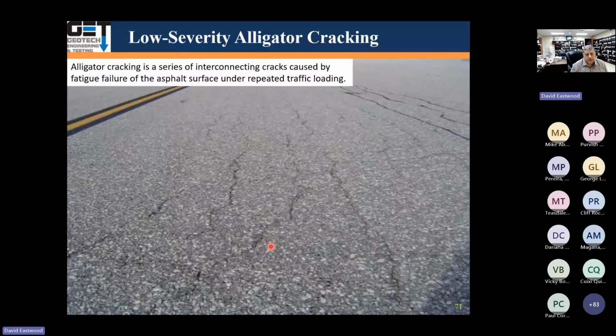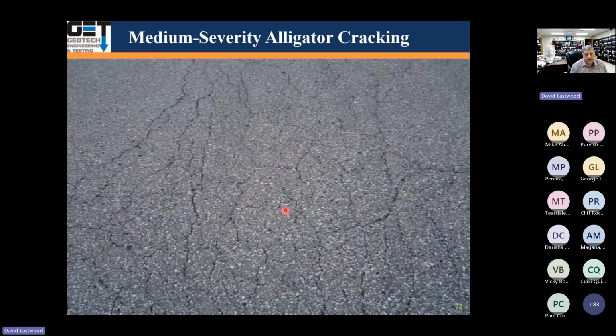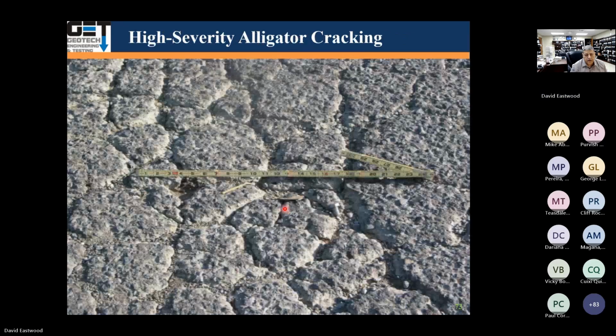Basically, some of the distress you see on asphalt pavements, some of them are alligator cracks. It's a series of interconnected cracks that are caused by fatigue failure from repeated traffic loading. And you can see a medium severity alligator cracking. This is a high severity alligator cracking.